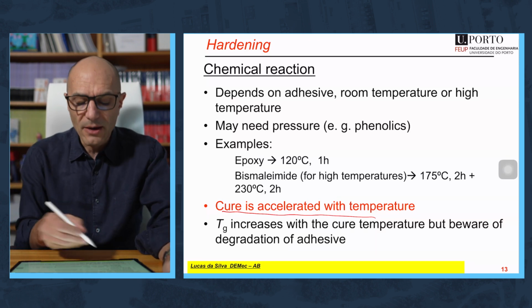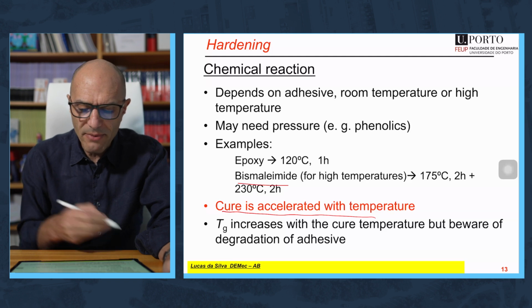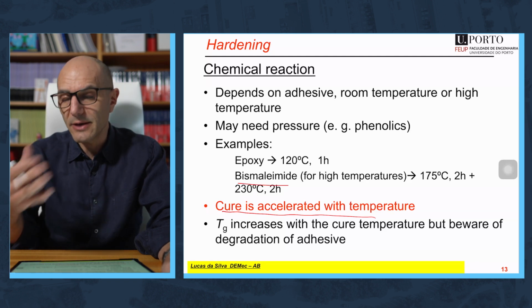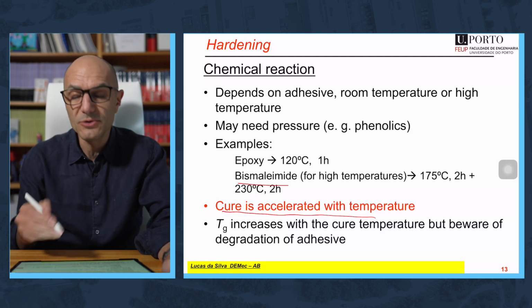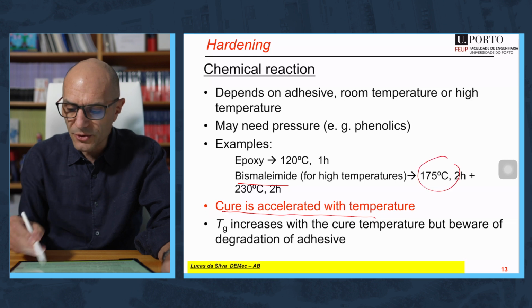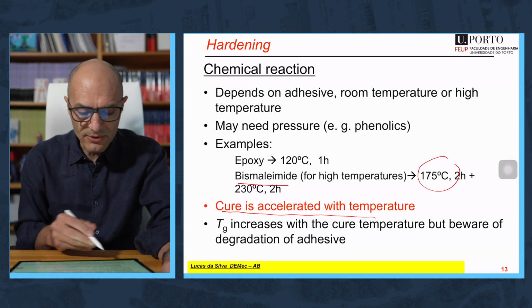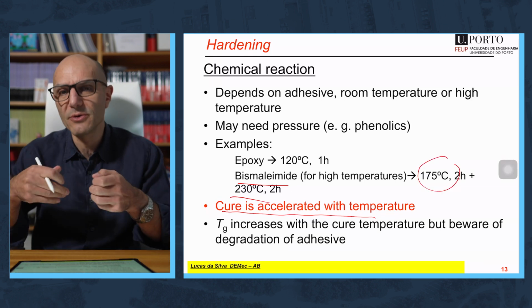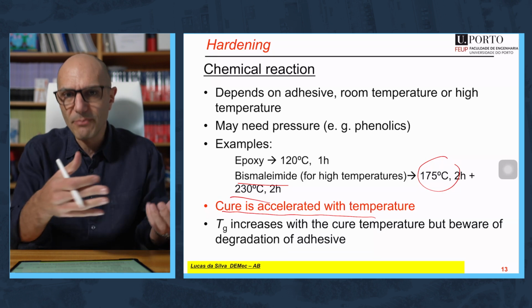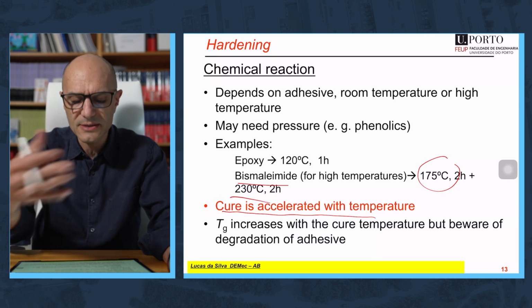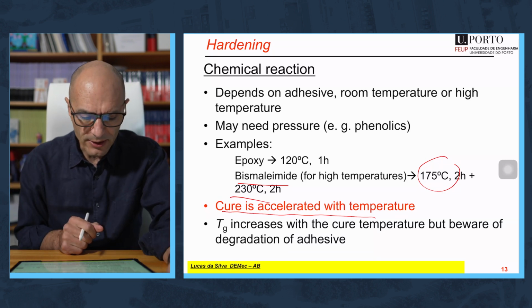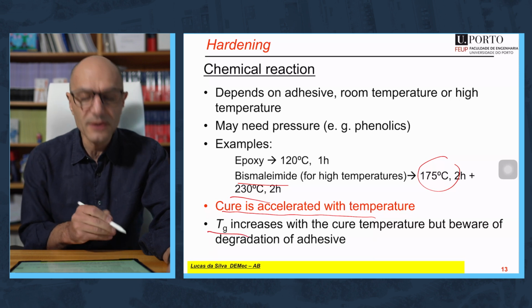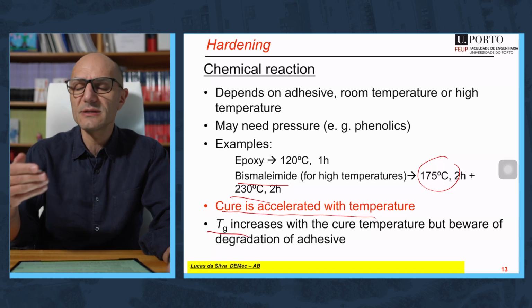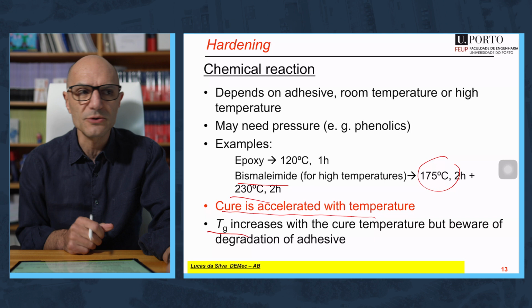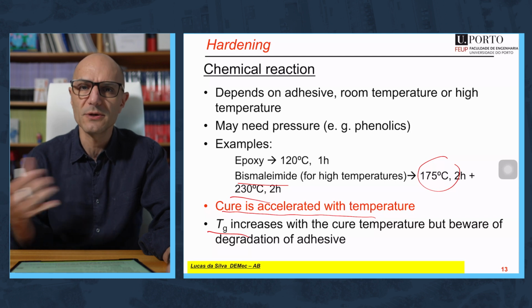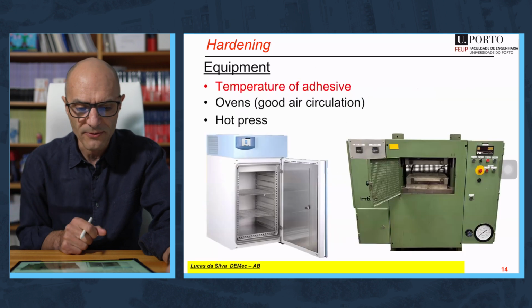Then you have the aromatic adhesives like bismaleimide that take higher temperature to cure. Typically you would do it in 2 steps. First a cure at typically 175, and then a post-cure. You remove the joint from the mold, to avoid too much residual stresses, and then post-cure at higher temperature. The Tg is increased when you increase the cure temperature, but we shouldn't abuse too much and use too high temperature, because then we start to degrade the adhesive.